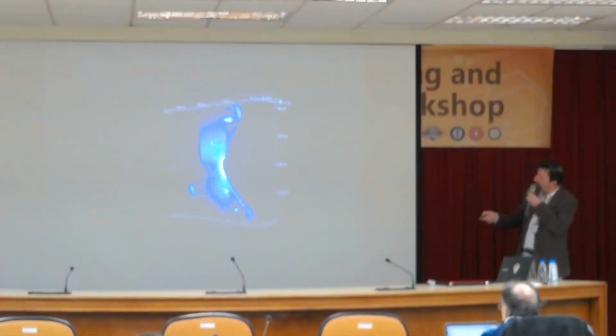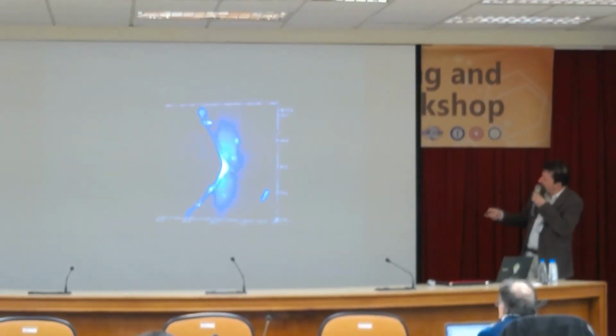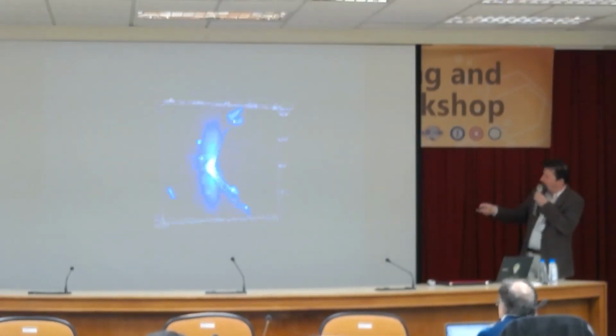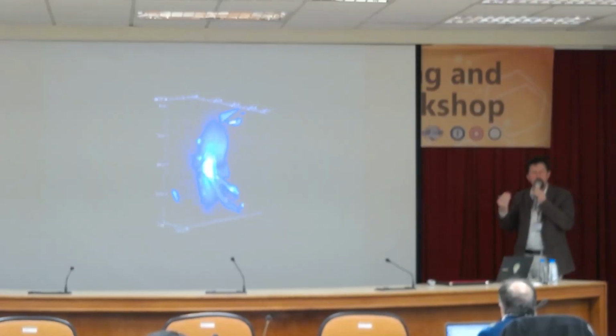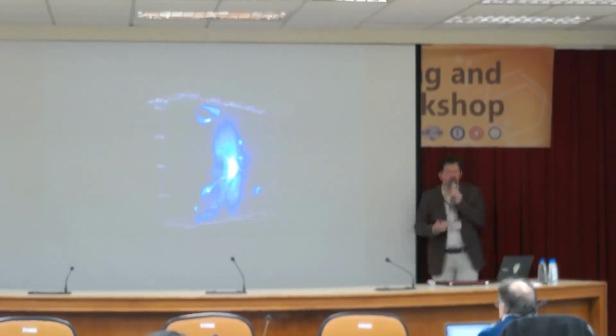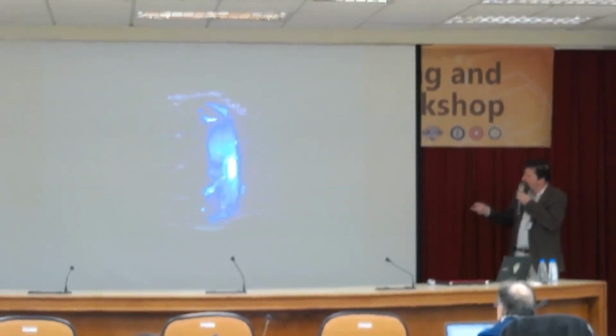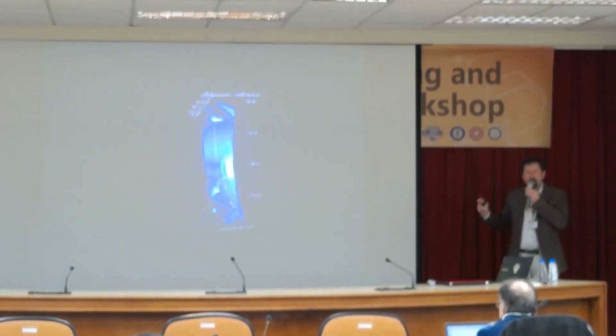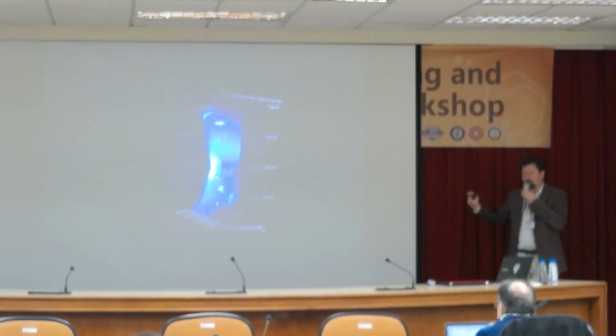So I'm going to show you here an image of what we can see. So this is now a 3D image of a crack, and here the light intensity, it's asymmetric because the intensity depends on depth, but you're actually looking at the damage at the crack tip. So you can see that it's very much a 3D process. And you could guess that from the first image where we're showing you these fibrils. But right now, we really are studying precisely this 3D process to see how this material can break at the molecular level and then go from the molecular level to the more microscopic level and connect that with fracture energy.